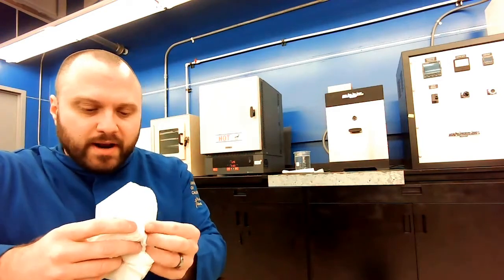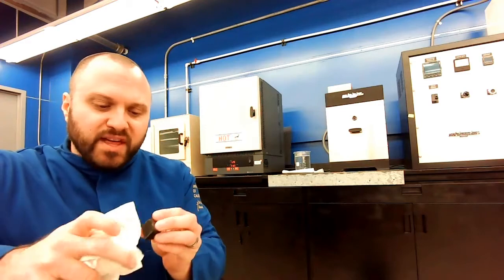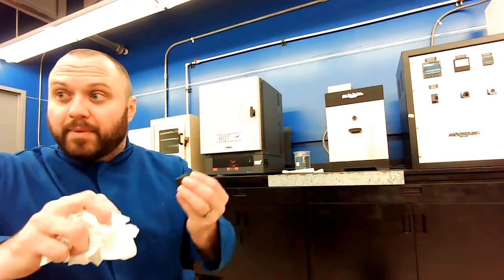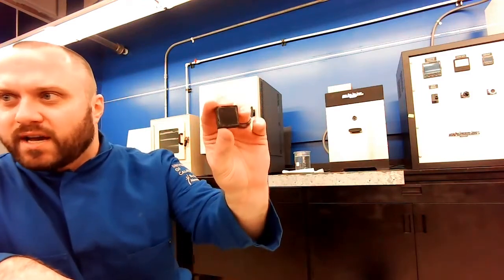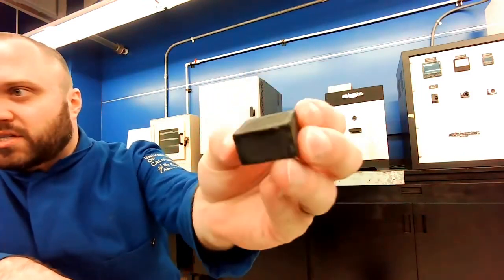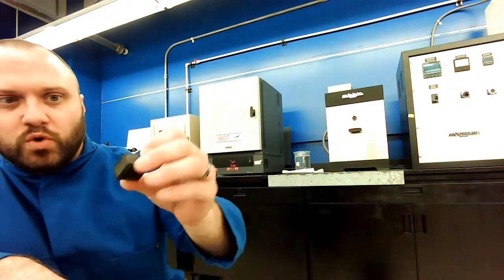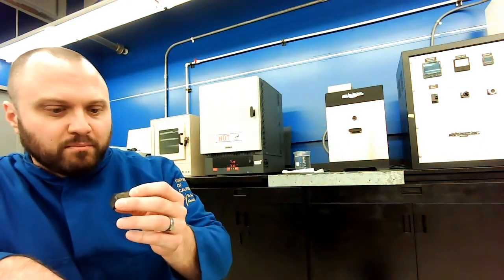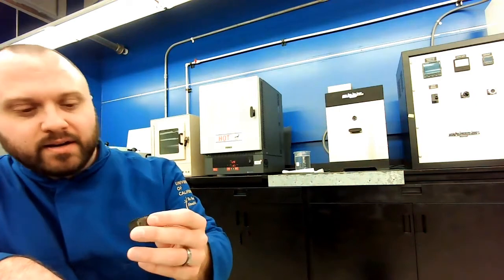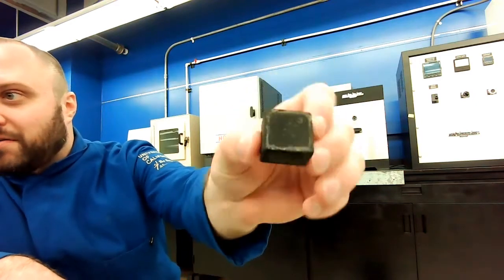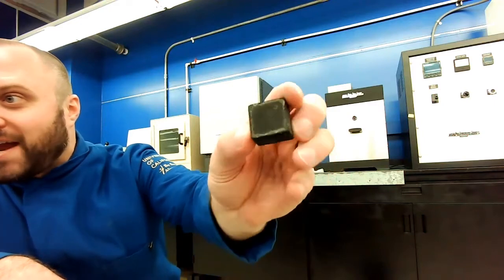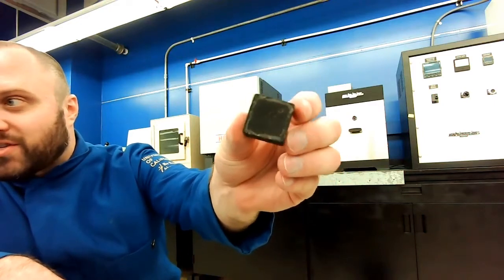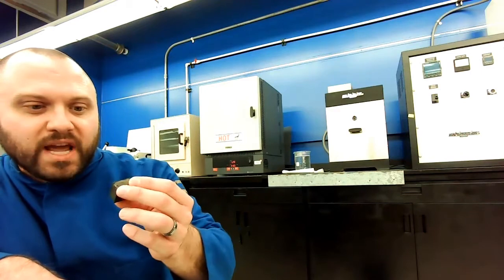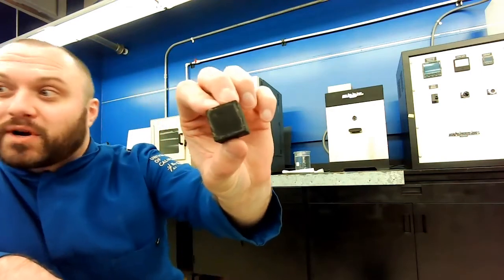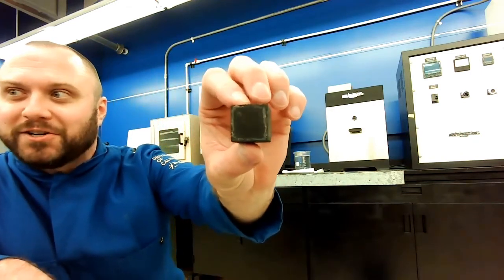And I didn't have to worry about it here, but if I, for example, had a really thin steel part, that rapid cooling could happen non-uniformly and the sample could warp or something like that. That's not really something to worry about with these. These are just blocks of material and we can sort of do whatever we want. But I will point out that this thing looks very different than it did before. It was shiny, well polished. All this surface oxide has formed. We gave it a lot of temperature. It didn't help that we put it in salt water. That was part of it too.